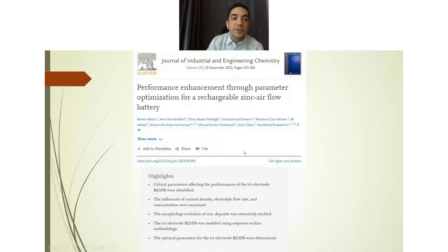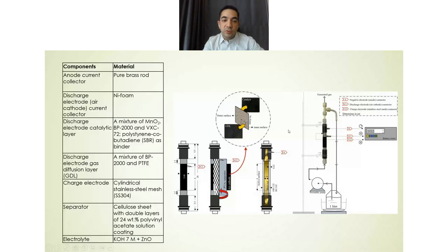So I'm going to introduce you to the second research paper. In this paper, parameter optimization was used to see the effect of operating parameters on the zinc-air flow battery. For this research, a tubular type zinc battery was used with a tri-electrode configuration, and a brass rod as an anode current collector was installed inside the tube. And for the air cathode, a manganese oxide based catalyst was used, and the gas diffusion layer, in which the composition of each layer you can find in a table. So basically, we have a hydraulic peristaltic pump here and an electrolyte tank to circulate the electrolyte within the cell.